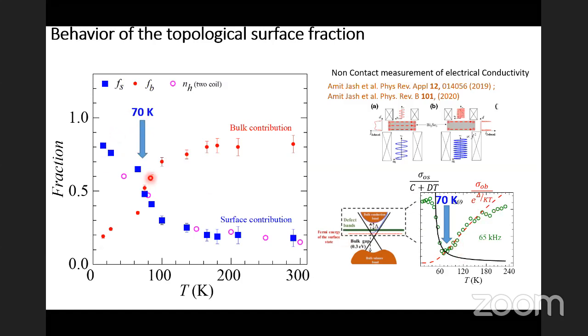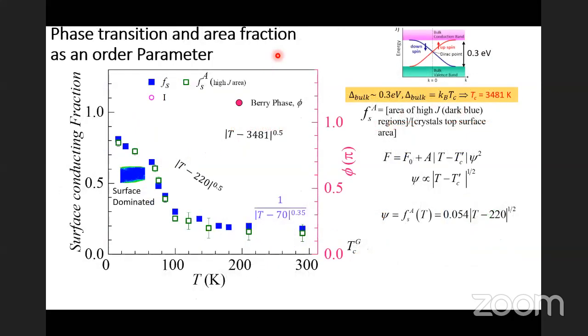So at 70 K, the moment the bulk starts conducting, you have this large drop in the 2D surface conducting fraction. And this drop actually corresponds to your uniform 2D surface conducting state breaking up into smaller and smaller patches. Okay. So if you recall, you can measure this region which has the uniform 2D surface state. You can measure the area of these blue regions, which are the high conducting surface states, and those are shown as open circles.